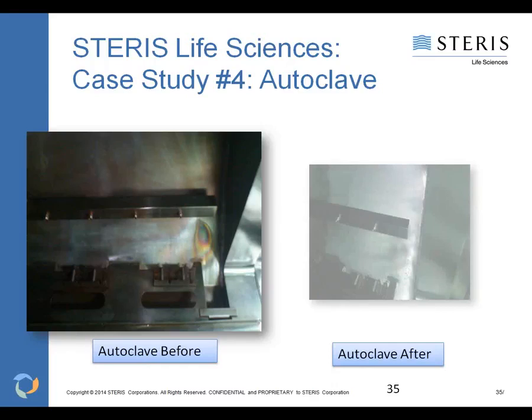So we have our untreated steam trap, one that was treated at 15% CIP 200 at 60 degrees for 4 hours. And then, again, to determine those experimental conditions that will work when you actually go out on the floor, you have your 20% CIP 200 at 80 degrees for 4 hours. So it actually took an increase in temperature. So this is a nice example of how you can play around with the percents, by bumping up that percent by 5% and by bumping up that degree by 20 degrees. You can see where you have a nice, bright, shiny metal on that third picture, but in the middle picture it just wasn't adequate. It just wasn't enough.